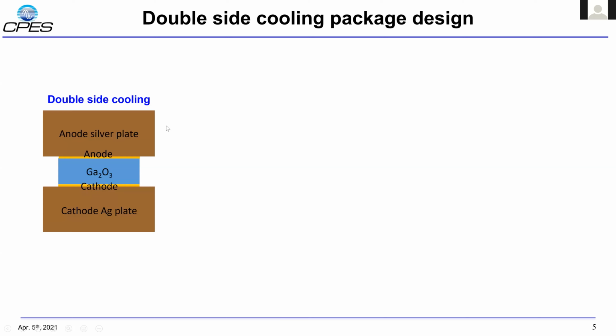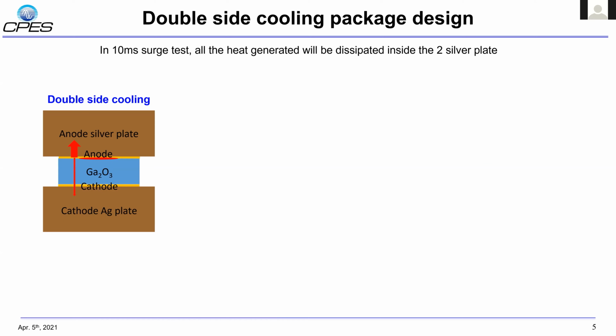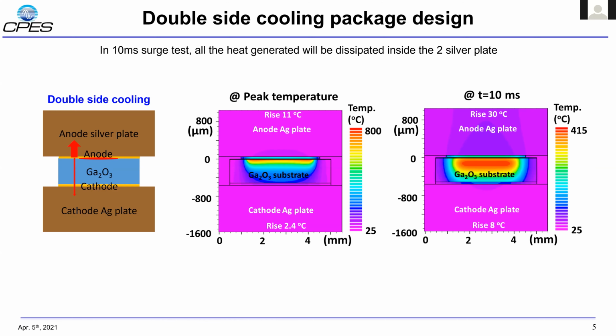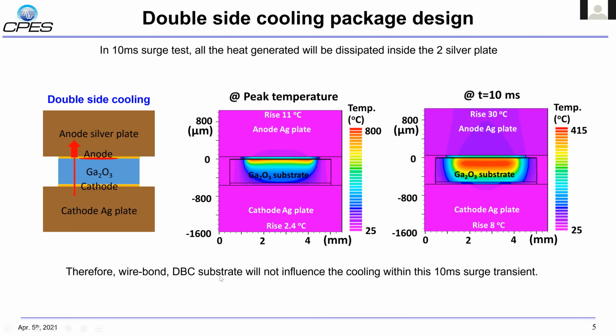Now let's talk about a double-side cooling package design, which allows the heat dissipation by the gallium oxide chip and from the Schottky junction simultaneously. In a 10 millisecond surge test, all the heat generated will be dissipated inside these 2 silver plates. From TCAD simulation, at the peak temperature moment, which is around 6 milliseconds, high temperature appears inside the gallium oxide diode. But at the boundary of the 2 silver plates, it is very close to room temperature. At the end of this 10 millisecond surge test, part of the heat is transferred to the anode silver plate, but the temperature of the anode silver plate is still low. Therefore, wire bond, DBC substrate, or anything else outside of these 2 silver plates will not influence the cooling within this 10 millisecond surge transient.